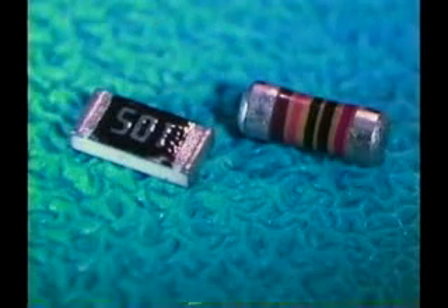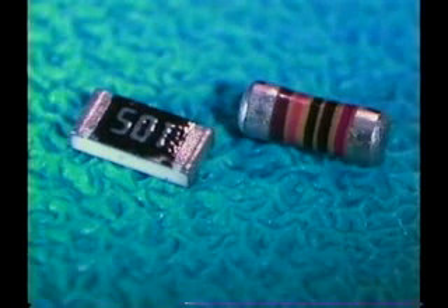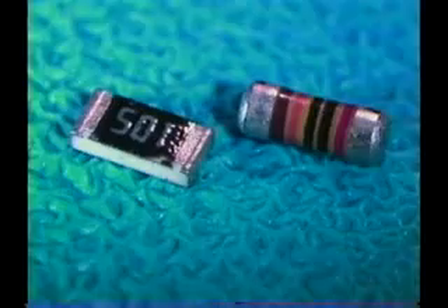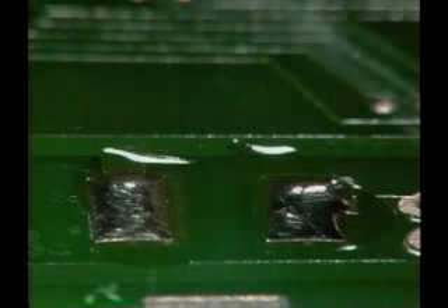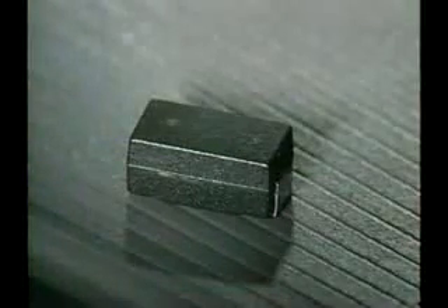The relative size of the component terminations will affect the amount of solder in the pre-fill. For example, a MELF component has more metal surface area on the termination than a chip resistor. This means that it will require more solder in the pre-fill to create an acceptable fillet. After both lands are properly pre-filled and cleaned, we need to add new flux. We'll be using the same tip sizes and heat setting from the previous removal operation.